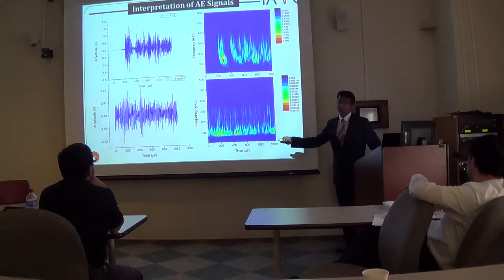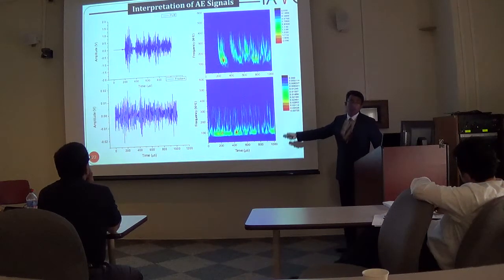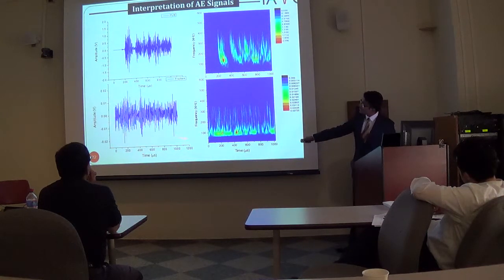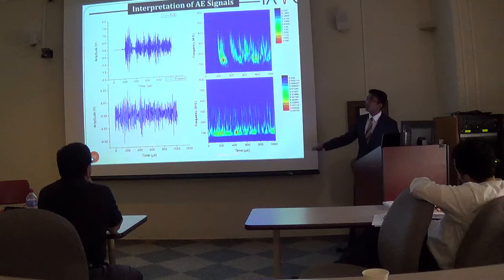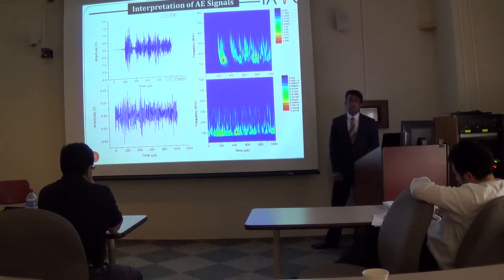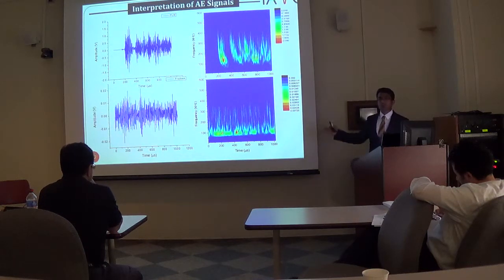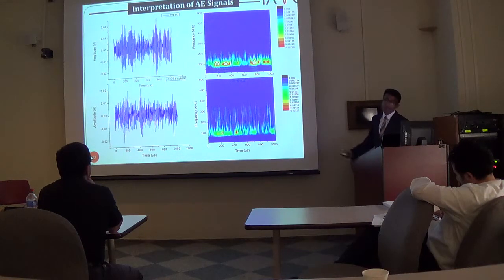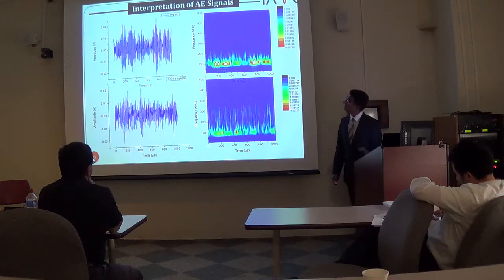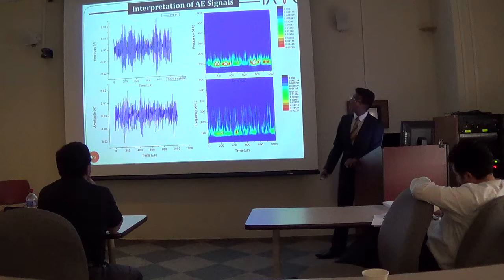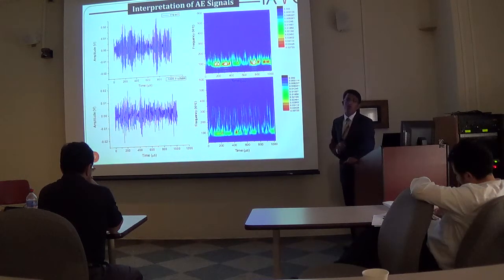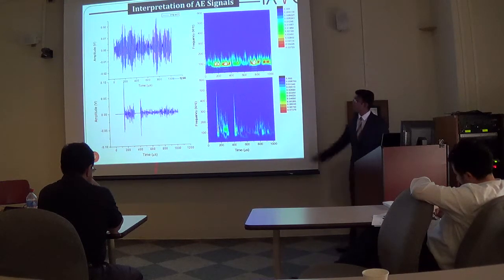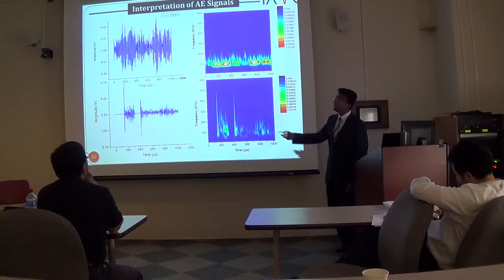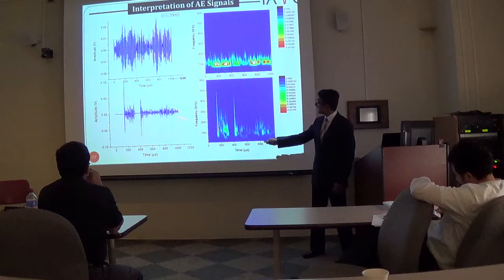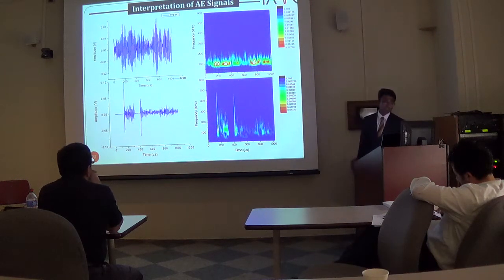Similarly, the continuous waveform that was extracted from the frictional source seemed to have a much different behavior compared to the PLB waveform. You can see a constant peak frequency centered around 100 kilohertz, but you can also note a wide spectral behavior of the frictional waveform, which is very indicative of a noise type of signal. Now, in comparison, the impact waveform, which also had a continuous type waveform, is seen to have a low peak frequency, as you see here, but importantly, it has a very narrow frequency behavior in comparison to the friction waveform. Finally, the EMI waveform is seen to have a burst type emission, and you can see a sharp increase in the frequency analysis as you see here, and you can see how the reflections also share similar frequency characteristics.